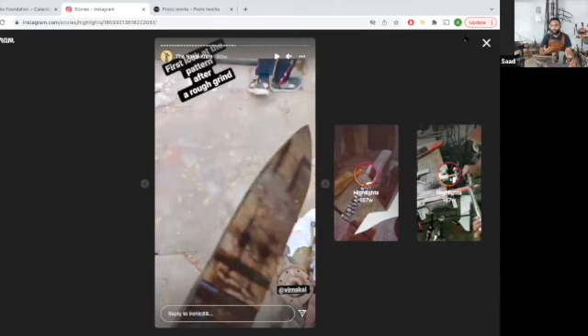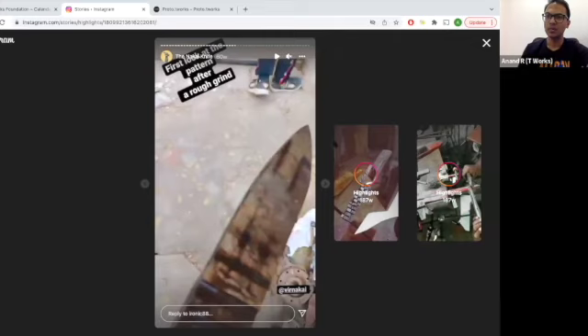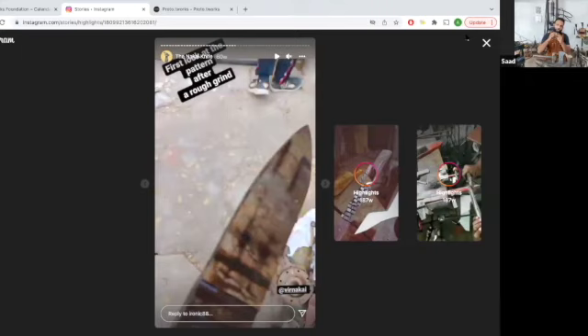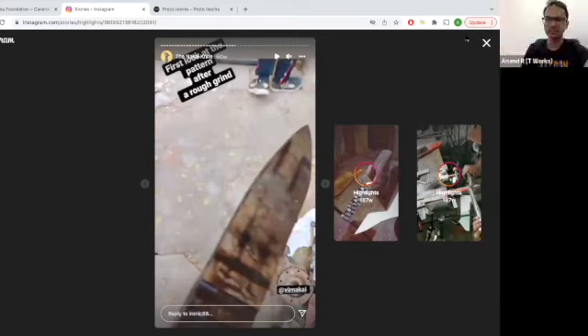The critical part about copper is that about 100 degrees before the temperature at which steel forge welds, copper melts and flows away. So there's a very narrow window where you've got to watch before the copper melts away from the billet and the steel is ready to forge weld, and you've got to do it. So I've got to experiment with that and see how to go about it. A lot of this learning is through trial and error, trying to understand material properties, trying to understand my own skill levels, because I'm teaching myself, and a lot of YouTube and forums and researching, and then going ahead and actually doing it.